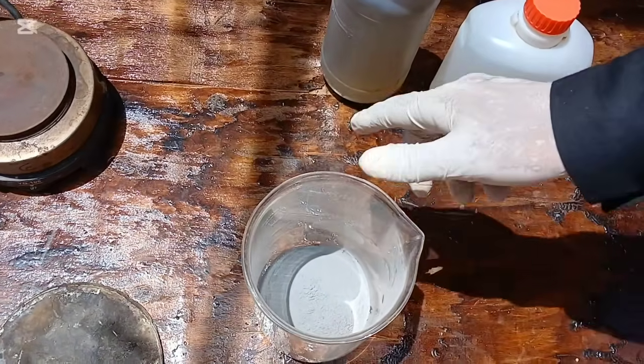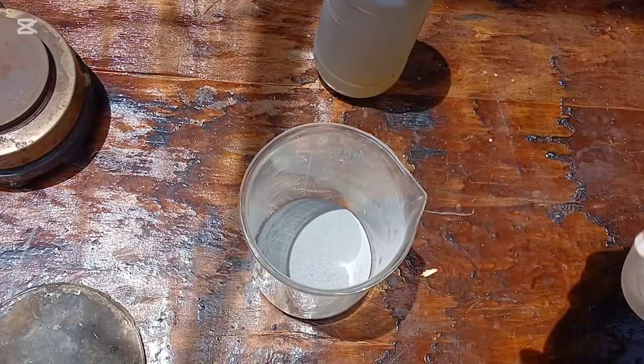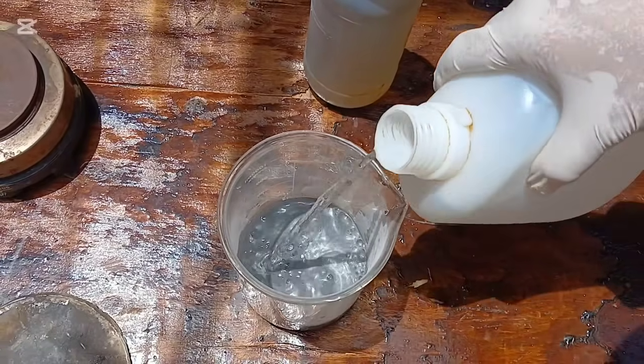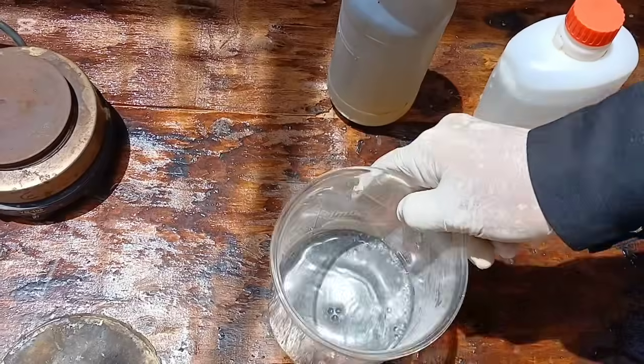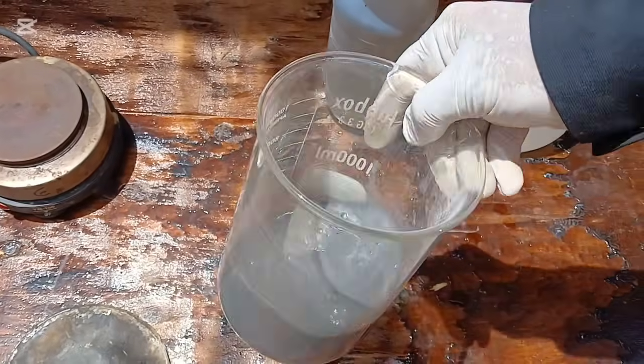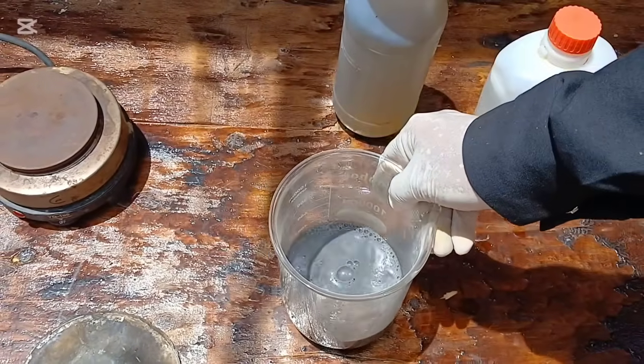At this stage, our goal is to remove cobalt and nickel, which have now been oxidized during roasting and are more easily dissolved. For this purpose, we'll typically use a diluted solution of hydrochloric acid or sulfuric acid. These acids are strong enough to react with the metal oxides, forming soluble metal salts that move into the solution, leaving the gold and iridium untouched, still in solid form.